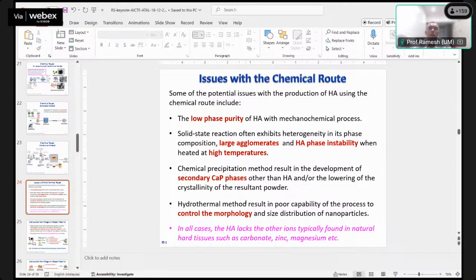Okay, and then sometimes you get secondary phase calcium phosphate formation, like tetra calcium phosphate TTCP, or even calcium oxide being formed. So these are considered impurity, although the body can accept TTCP or CaO, calcium oxide, in the body. But when you use it for implant, a solid HA implant, remember I said earlier that we want the implant to remain as implant for a long period of time. But once you have degradation taking place, HA transforming into secondary phase, it causes an issue. It loses its integrity.